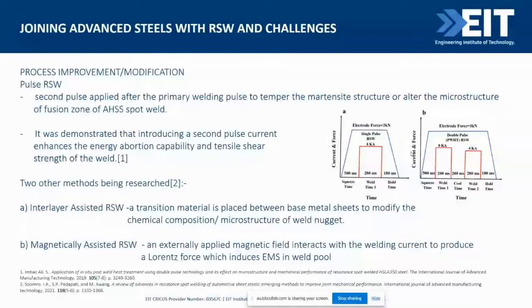Now, this has not really been looked into as part of actual production, but in research, there is a lot of research being carried out. Right? One of the ways where the advanced steels can be spot welded was found by having something called an interlayer. That means in between the metal sheets that you're welding, you place a separate steel. All right. We call this the interlayer. In fact, the same method is being used even in aluminum as well as magnesium. All right. With the use of an interlayer in between, it was found that the microstructure can be modified in such a way that the weld has reduced martensite content, more of an austenite content.